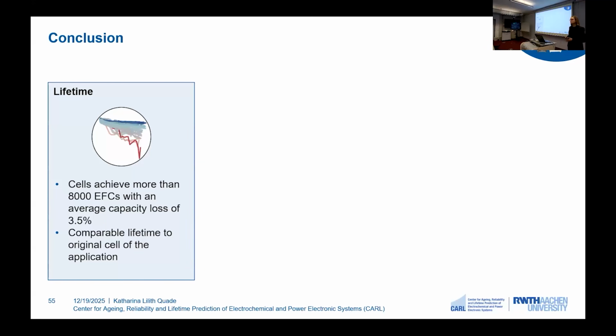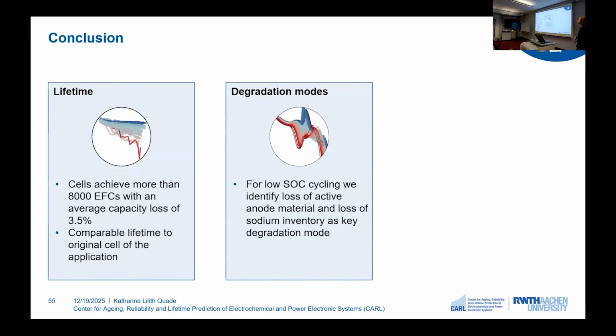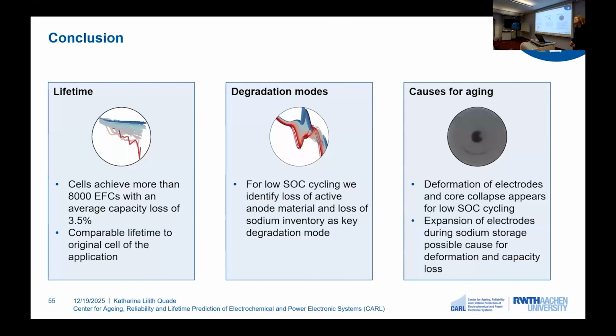However, we did some further analysis because we observed very high capacity fade in the lower SOC cycling conditions. Therefore, we did some non-invasive degradation analysis, and we could identify for the problematic cycling conditions that we have loss of active anode material and also loss of sodium inventory as key degradation modes. We also took CT images, and we could see that only for the lower SOC cycling conditions, we had core collapses. We think this is because of the sodium storage mechanism in hard carbon and the higher expansion for the lower SOC conditions. However, for our application, this is not a major concern because, if you remember, we always cycle in the mid-SOC range.